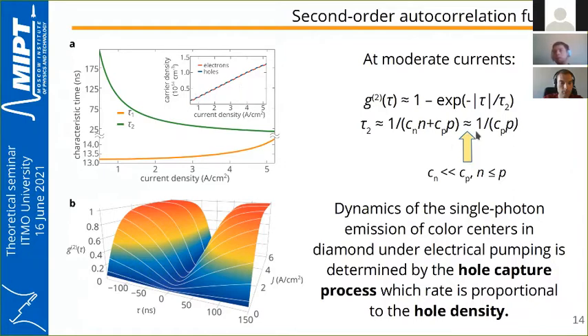And what we obtain is that tau2 is just 1 over Cp times P. And in this case, we see that the dynamics of single photon emission of color centers in diamond under electrical pumping, characterized by the G2 function, is determined by the hole capture process, whose rate is proportional to the hole density. And thus, we propose a new method of determining the local hole density.